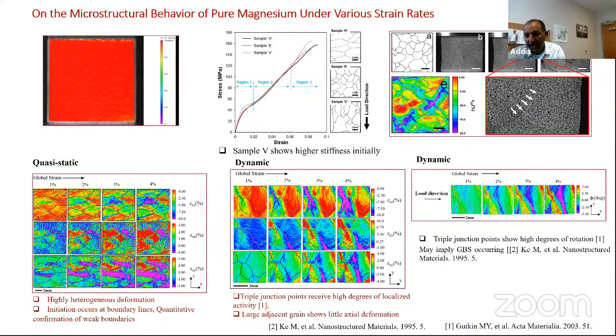We also observe in the dynamic case that the triple junction points receive a high degree of localized activity. You can see that when three grains join, that's where you see large deformation mechanisms. Also, the grains adjacent to the large grain show very little axial deformation. We are also able to measure rotation. We measure the rotations of the grains, and again the triple junction points show a high degree of rotation, and this also implies that there is grain boundary sliding occurring in these materials. This is purely based on these correlations.